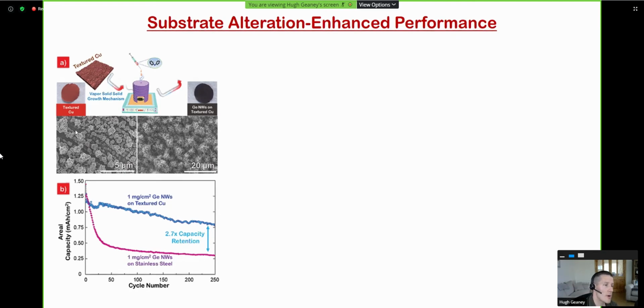So we looked at textured copper as a current collector and grew the wires directly on it. One of the benefits of this was that we could grow the wires directly on the current collector without having to do an initial evaporation of a catalyst material. So we had previously established that you can grow nanowires directly from copper foil. What happens essentially is you form these copper germanide seeds in situ on the substrate, and then the nanowires will grow from those. So what we were able to do was get very nice loadings of the germanium nanowires grown directly on the copper current collector here.